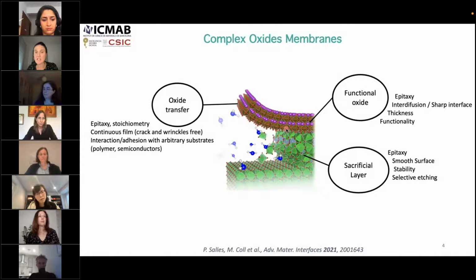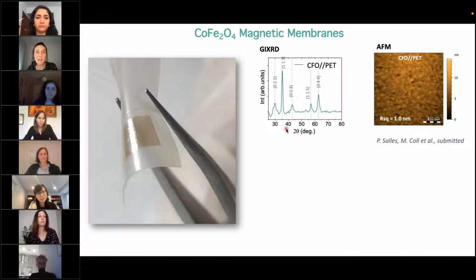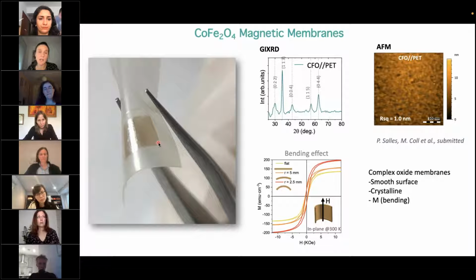So after a very detailed optimization of this process, we've been able to prepare membranes of binary oxides and also complex oxides. And I will show you here as an example these cobalt ferrite membranes, which are crystalline, as you can see from here, also very smooth. And the fact that we can transfer it on flexible substrates, we can also investigate how, for example, the magnetization varies with the radius of curvature of the polymer.